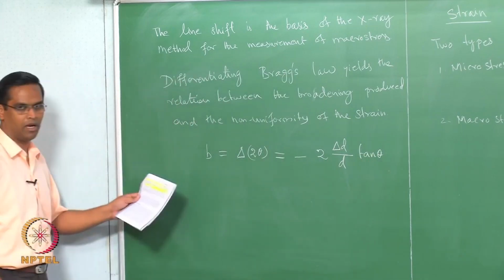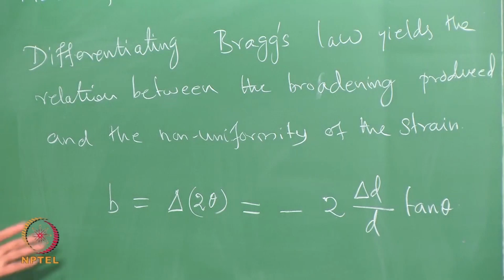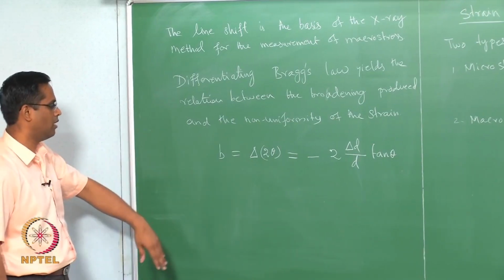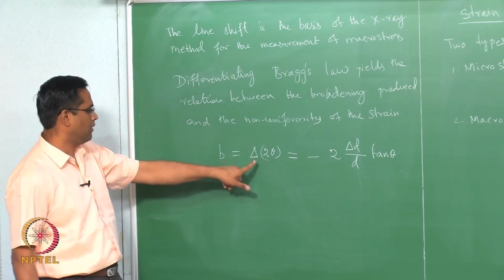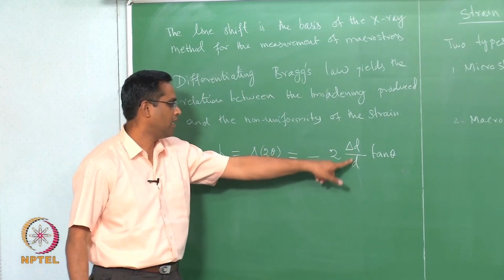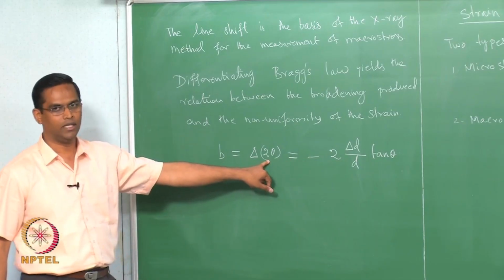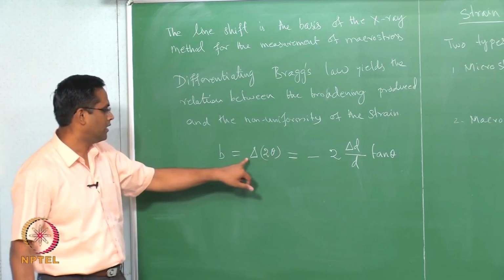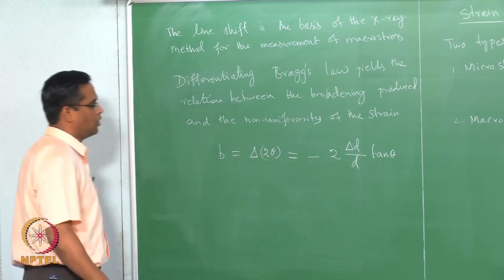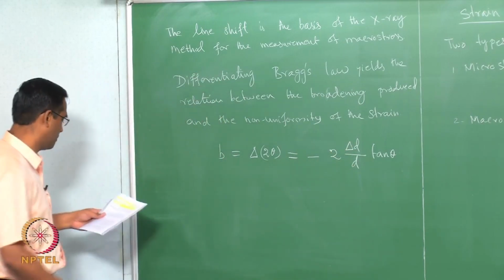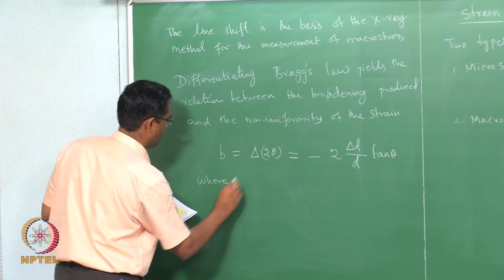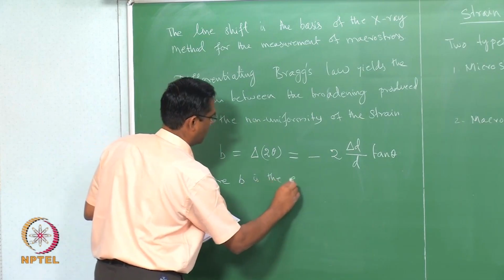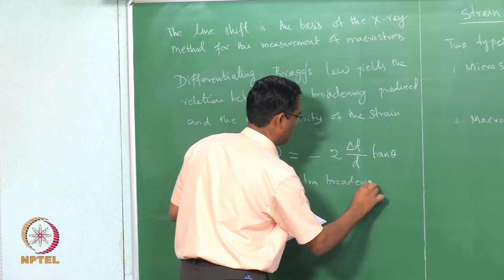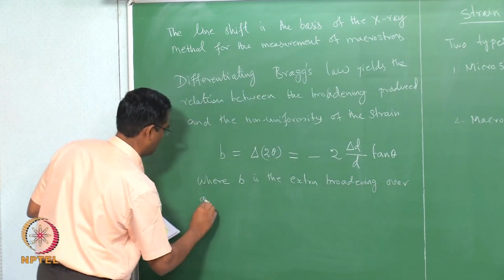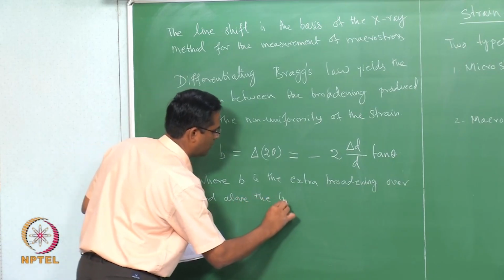So, you differentiate lambda equal to 2d sin theta, using the u v dash plus v u dash kind of formula, and then you will be able to derive a relation: delta theta is equal to 2 delta d by d tan theta, but what we measure is 2 theta, not theta. So, delta 2 theta can be written as minus 2 delta d by d tan theta. So, this is the expression where B is the extra broadening over and above the instrumental broadening.